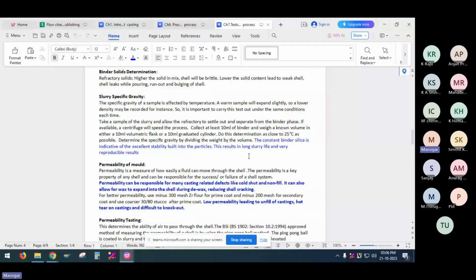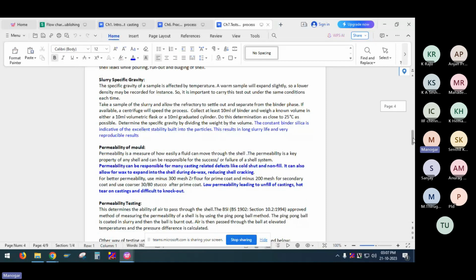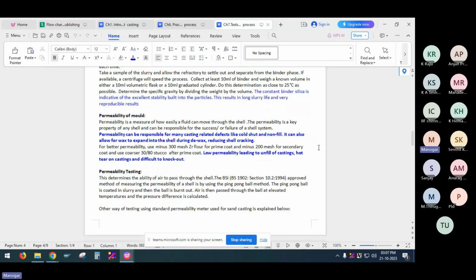The constant binder silica is indicative of the excellent stability built into the particles. This results in long slurry life and very reproducible results. So that's why slurry specific gravity measurement is an important thing. And permeability of molds. So you know that permeability is important in all the processes, whether sand casting or shell molding or other processes, to drive away the internal gas and avoid any air related defects.